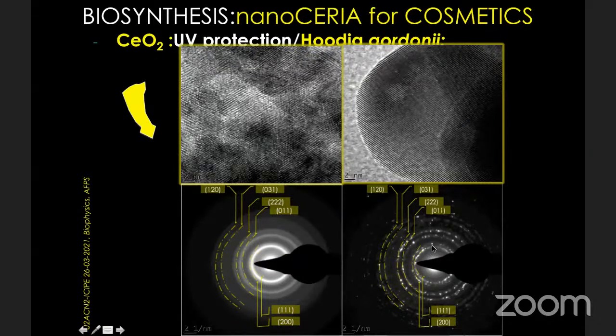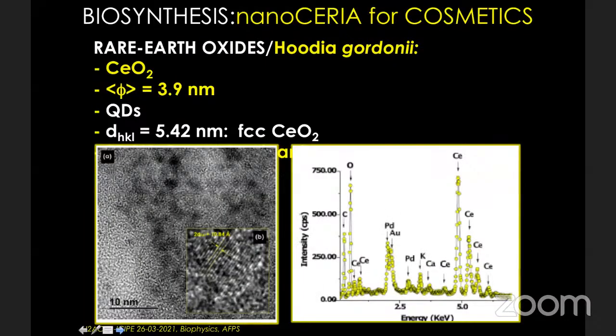As you can see clearly, spots of diffraction, while here is an annular type of diffraction, equivalent to the amorphous type but with a local ordering, but here it's highly crystalline. And it takes place at room temperature without any acid or any artificial base. It's only with phyto compounds from Mother Nature, straightforward. And when you look, you can clearly see that they are very small nanocrystals. They are quantum dots, colleagues.